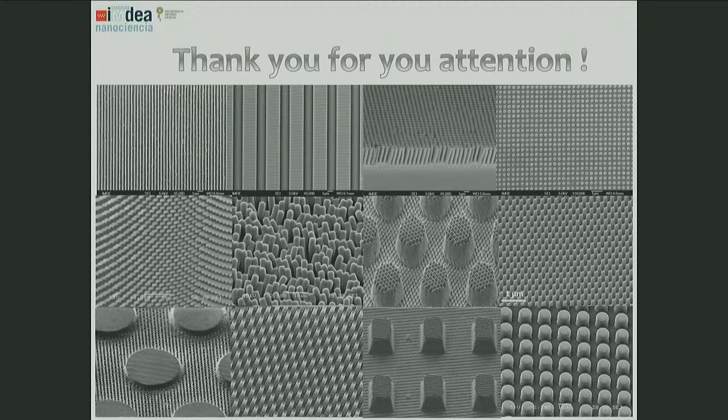Yeah, I would say most of these properties are actually achieved by the geometry, but obviously the material properties are implicit. For example, if we talk about wettability or hydrophobicity, the rule is normally that when we have a material that is hydrophobic and you make a structure, it becomes super hydrophobic. But if we have a material that is hydrophilic, when you make a structure, it becomes super hydrophilic. For example, cellulose, paper. Paper is hydrophilic. You put a drop and it wicks into the paper. It is wetting totally. So that's a clear example that the material properties are very important as well.